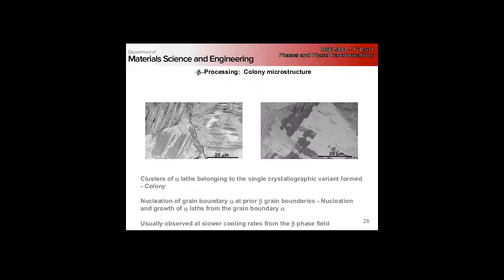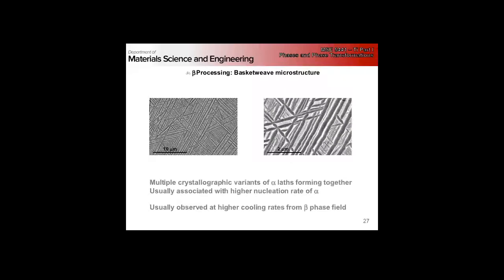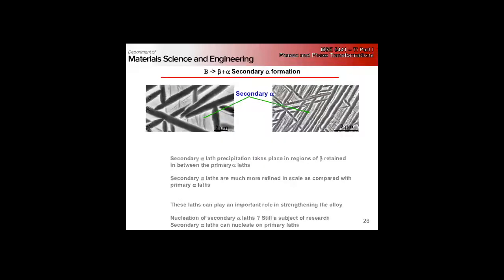If we cool faster, we get a basket weave structure where instead of regions of one crystallographic variant, we get interspersed variants. This is a higher nucleation rate of alpha — not just from the grain boundaries, but intragranular nucleation. This happens at a higher cooling rate with larger undercooling. Secondary alpha forms in between on quenching and is fully developed during stabilization. The actual nucleation and growth of the secondary alpha is still a really open area of research.